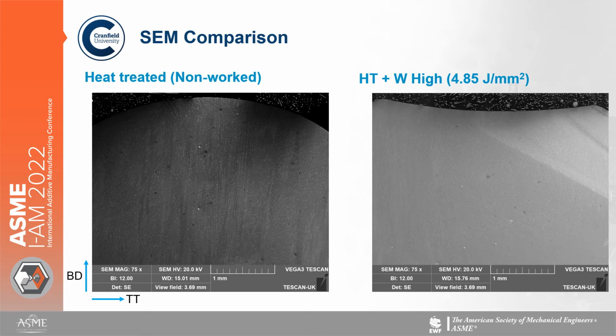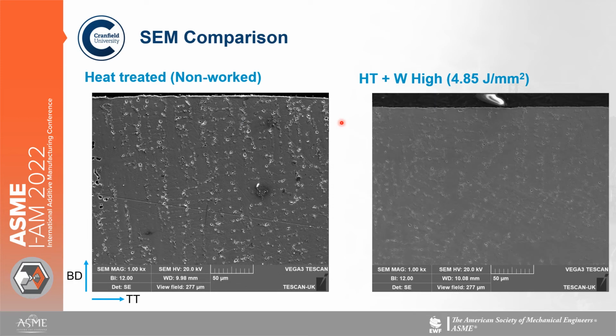So then comparing the two samples under the electron microscope, this is very zoomed out at 75 times zoom, but we can see our indentation here again and our non-worked material here. So if we go to 1000 times magnification, there's not a great deal of difference to be observed in either of the materials.